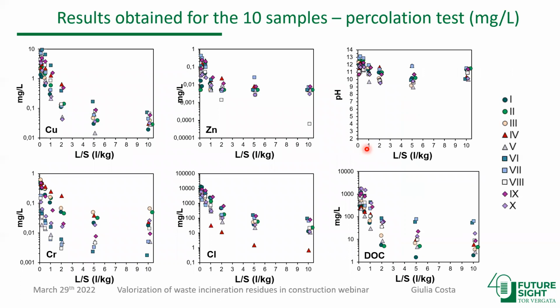Now here are some of the results of the tests we have been performing. So we see the results for all 10 samples, the average values for some specific elements, reported as the concentration in each eluate as a function of the liquid to solid ratio. So we can see that basically the first eluates of the percolation test are the ones that contain a higher concentration of elements, which tends to decrease for larger liquid to solid ratios. And let's say it can decrease by various orders of magnitude, looking at copper, or less looking at zinc.